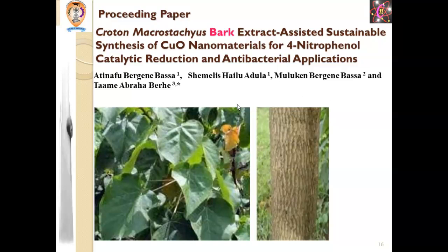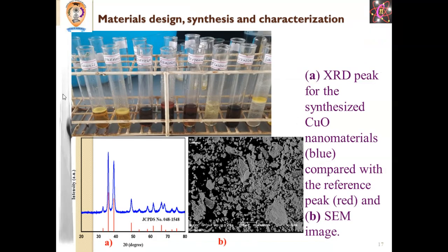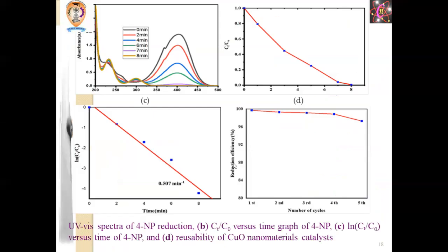So our work is also very interesting, green, and impactful, not in one way, but in many. This was the synthesis procedure and the material design approach. As you can see, we compare our catalyst diffraction pattern with the JCPDS pattern, and you can see it perfectly matches the JCPDS diffraction pattern. This indicates we successfully synthesized our material and can apply it to the intended purpose.